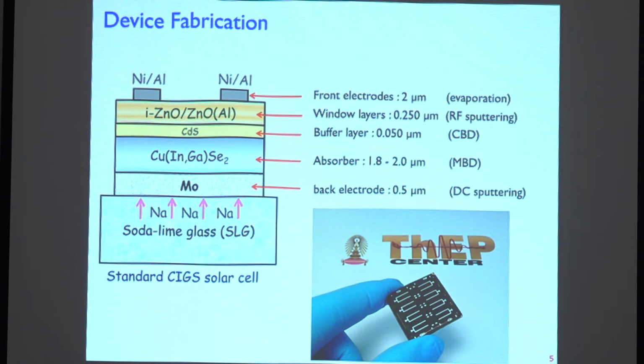And the upper layers are the N-type semiconductor. I forgot to mention that CIGS is a P-type semiconductor. And zinc oxide is used as a window layer so that the sunlight can come through. Aluminum is used as the front electrode. This is what the lab scale device looks like, 3 by 3 centimeters square. Okay, that's the structure. For the material study, we will not complete the whole structure. We will fabricate up to this layer: CIGS on molybdenum on soda lime glass.